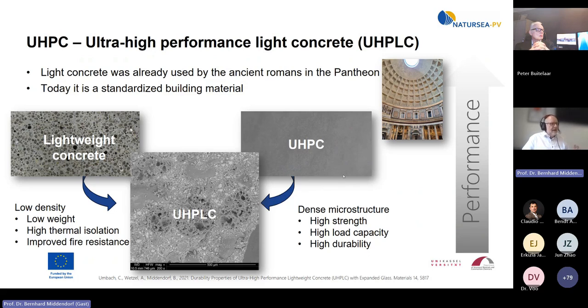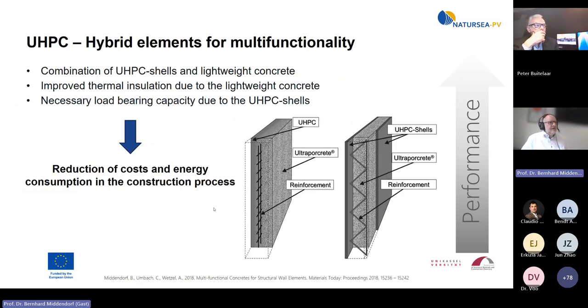We use this idea and use the matrix to prepare a lightweight concrete. That means we call it UHPLC, ultra high performance lightweight concrete. That means we have a strength approximately in an area about 100 megapascal, but we can then combine it with UHPC, with original UHPC.